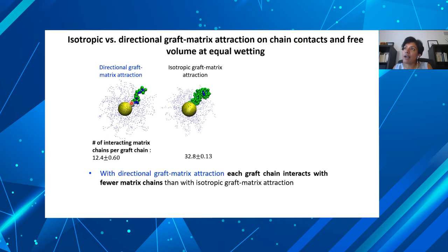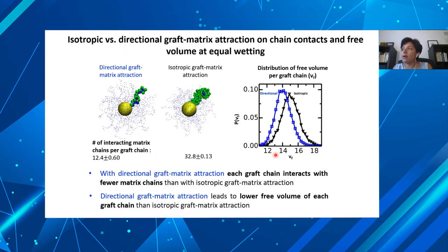So if you see, each grafted chain in the case of directional interaction only interacts with a few matrix chains as compared to the isotropic, where it interacts with many more. Furthermore, the free volume per graft chain, so this is important in thermomechanical properties, that distribution is lower, so everything's tighter in the case of the directional interactions compared to isotropic. So while wetting may be the same, the chains themselves likely are behaving differently. And so the thermomechanical properties and rheological properties could be different, even if the equilibrium wetting is the same. So that's important to see.